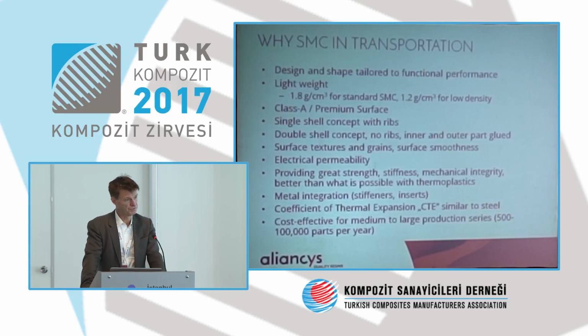The surface structure is a very important parameter, very smooth, because everything which is deviating from the surface, you see with your eyes right away. And this is what we are going to prevent. So there are electrical properties, especially when you go into a deck lid, where all antennas are installed meanwhile. This is also another big benefit, because if you have a steel deck lid, the radiation for the radio system will not come through. So you need a composite material, and that will also at the same time resist a certain temperature.